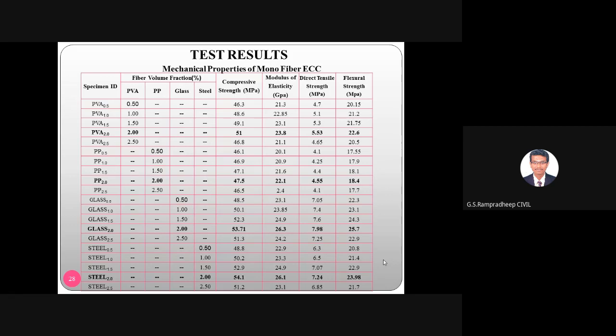Just see the mechanical properties of the monofiber ECC, where he has classified into 4 fibers, as I already pointed out: PVA, PP, glass and steel. For PVA, he is going to a maximum of 2.5%, because in one journal he went up to 2.3. So in our journal, the maximum he is testing is 2.5%, at an interval of 0.5%: PVA 0.5, 1.5 to 2.5. For that, the fiber volume fraction of the remaining types, PP, glass and steel, is 0. And similarly for PP, glass and steel, the corresponding fiber volume fractions are mentioned in this table.